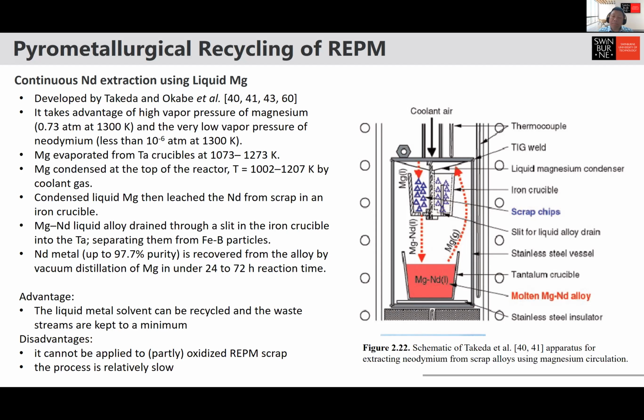Sorry, yeah, liquid alloy, and the process keeps continuing. It keeps recirculating. So basically, more and more neodymium is getting extracted from the scrap chips. You'll end up with just the Fe and the boron particles, right? And more of the neodymium is concentrated in the magnesium liquid at the bottom there, right? So once everything finishes, almost all the neodymium goes into the bottom. Then you can separate the magnesium by, for example, vacuum distillation, and you can get quite a nice high purity, up to 97.7% neodymium from this process.